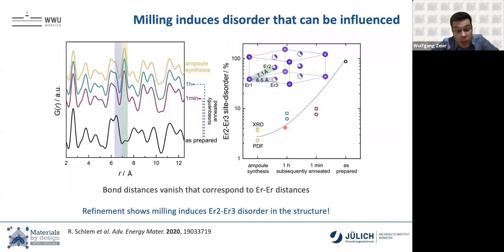Qualitative is not quantitative, so we can refine these PDFs, and of the crystalline material, you can also refine the diffractograms. And what we see is that in the ball milled sample, there's an erbium 2, erbium 3 disorder that is roughly 97%. So when you ball mill the material, you actually already locally form your structure, but it's not ordered. You have erbium sitting more on this side than on this one. And the more time you give it in the furnace to relax into its thermodynamic minimum, the disorder decreases. It's still there, even in the ampule synthesized material, but it's minimal. So we have this disorder in the structure.